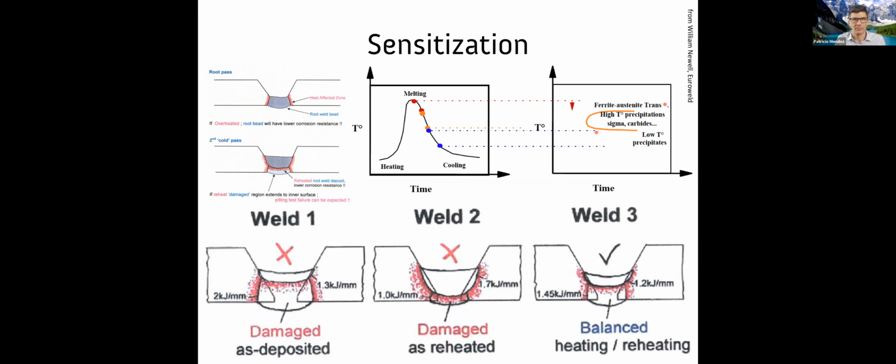At low temperatures, the diffusion is so slow that even if the carbides wanted to transform, they don't have the kinetics to transform. But there's a sweet range, right, between more or less 1200 degrees and 800 degrees, at which this transformation of chromium and carbon in solution into precipitated carbides, doing everything wrong for us, is happening very fast.